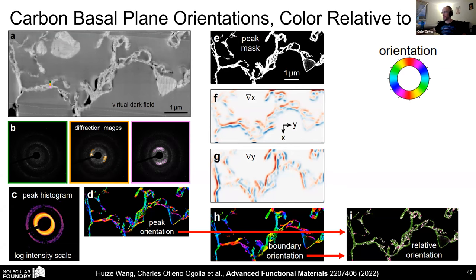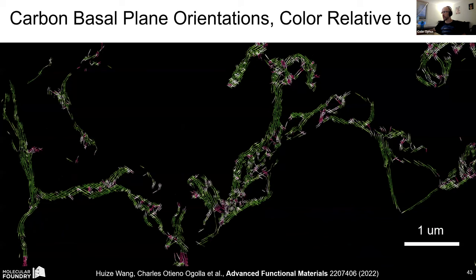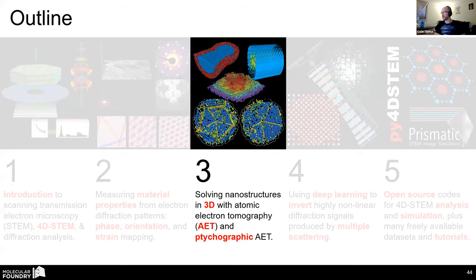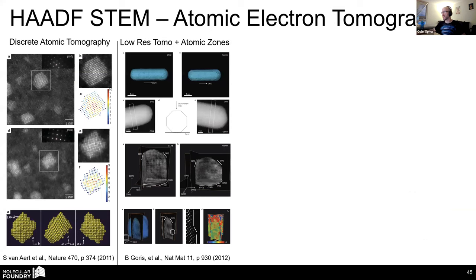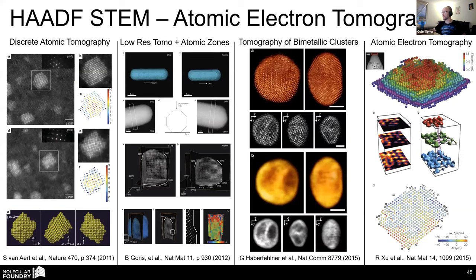If you subtract those from each other, you get the relative orientation between the carbon basal plane and these hollow pores. I'll just zoom in to show, colored in green, 0 degree orientation between the pore and the wall here, and in purple, 90 degree orientation. And you can see a strongly, very statistically significant orientation relationship between the carbon basal plane and these open pores here.